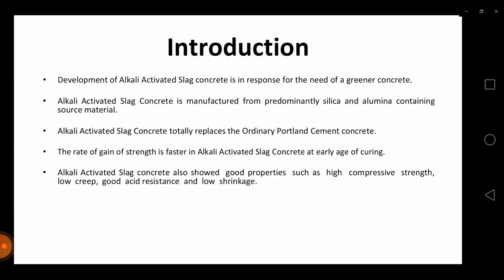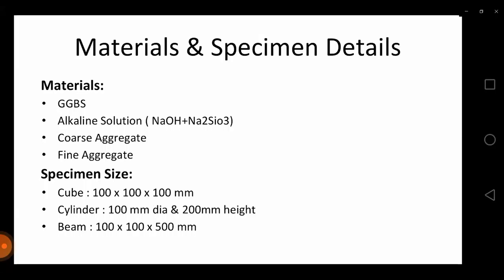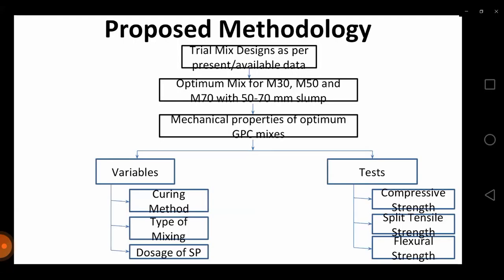But again, it has some good properties. It is rich in mainly the silica and alumina content as a source material. And it is rich in early gain of the compressive strength and low creep, good acid resistance, and low shrinkage also. So when it comes to the research part, I have considered these materials and the specimen sizes. And you can see here, we have not considered any cement and water.